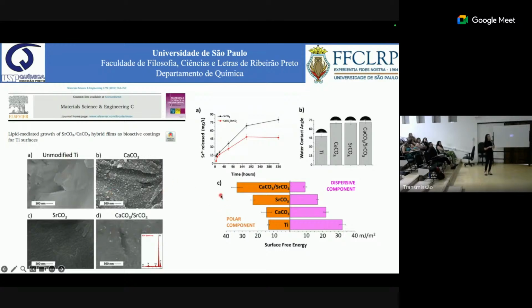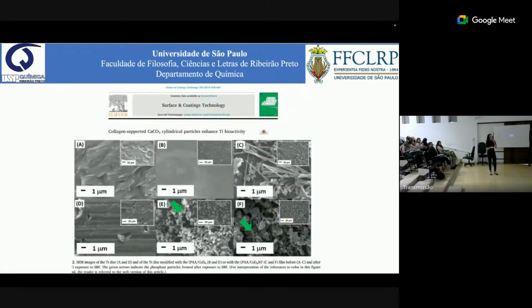We use it like here. It's just another example. We use this kind of films not only to deposit calcium phosphate on the surface of titanium, but we also can use this to deposit carbonates. We can measure the surface energy of the surface after the deposition of the films. We can also track the release of ions by the surface. We can use this kind of films also to deposit, after depositing collagen, these very beautiful nanotubes composed by calcium carbonate. So more than a model, these bilayers are very versatile to produce functional biomaterials.